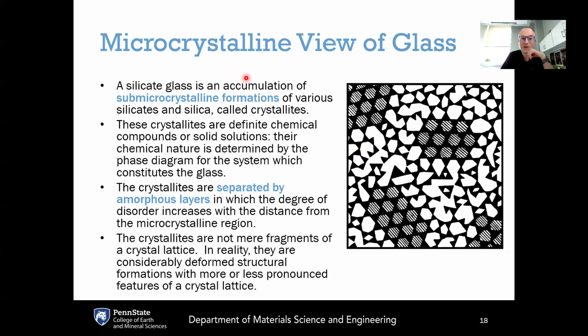They proposed that, for example, a silicate glass is an accumulation of submicrocrystalline formations, so nano-sized crystals of various silicates and silica, and they called these crystallites. These crystallites are definite chemical compounds or solid solutions. Their chemical nature is determined by the phase diagram for the system that constitutes the glass. These crystallites are separated by some sort of amorphous layer in which the degree of disorder increases with the distance from the microcrystalline region. And the crystallites are not mere fragments of crystals. In reality, they are considerably deformed structural formations with more or less pronounced features of a crystalline lattice. So this was a debate that went on for decades.